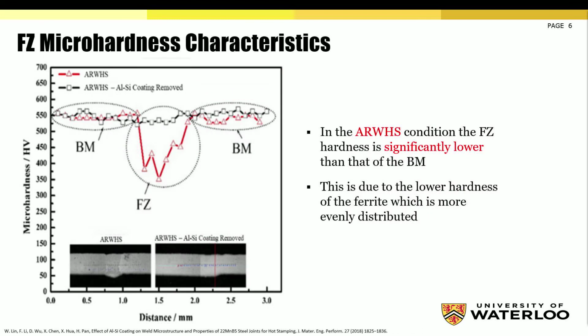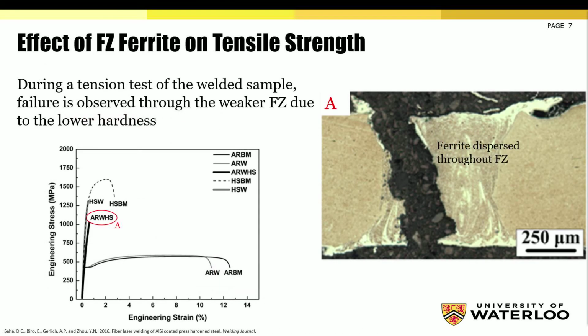Now, what are the implications of a dual-phase fusion zone on the mechanical properties? Well, to answer this question, we must consider the differences between the two phases, the most important of which is the fact that the martensite phase is significantly harder than the ferrite phase, clearly showing that the weld fusion zone is much softer than the bulk material. The softer fusion zone significantly reduces the load-bearing capacity of the joint, and the joint efficiency is about 74% of the base condition, which is extremely poor and happens to be a huge problem from a safety and crashworthiness standpoint.